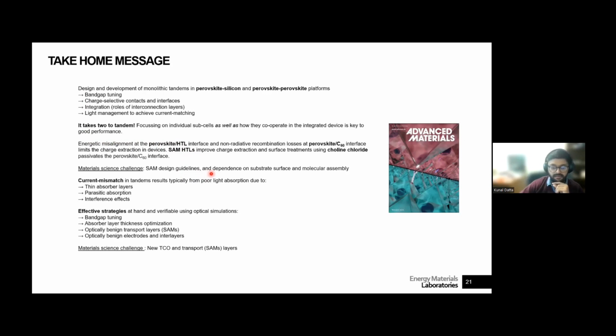But there are some design considerations, like it needs to be a carbazole, it needs to have a phosphonic acid linker, but I don't think there's as much work on, or understanding, at least, of how these SAMs organize, how they interact with each other, and how they depend on the substrate that they're being deposited on. And one key SAM that is being focused on right now, there's been a few papers in the last 2 or 3 weeks, is this Me-4PACz SAM, which is a nightmare to spin coat because of the de-wetting. But recently there are some groups which have figured out ways to have better wetting on this layer. So there is still quite some work on that front, which is quite interesting.